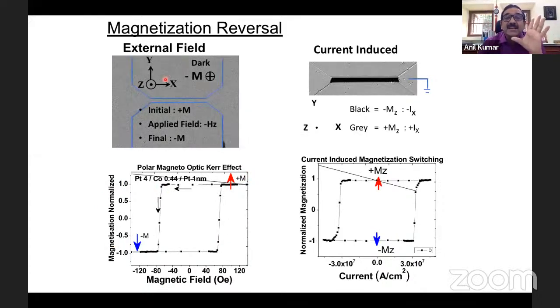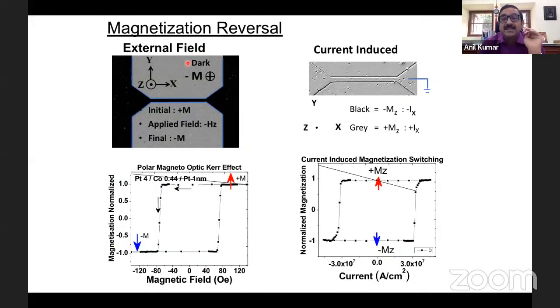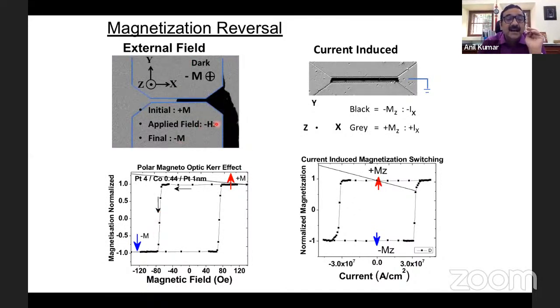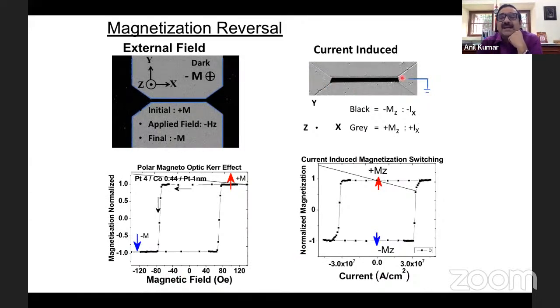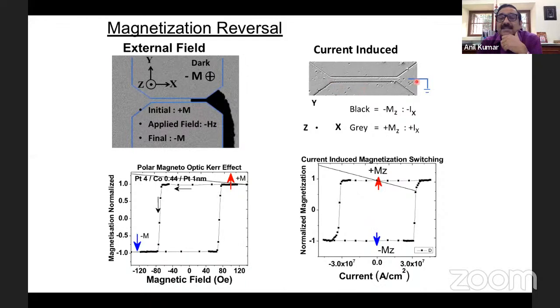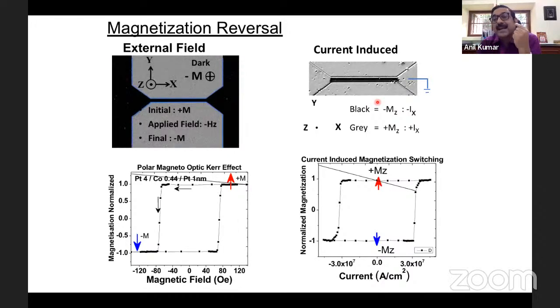So this is a field-induced magnetization reversal, because the applied field is HZ, which is perpendicular to the plane. Now the same system, now I pass electrical current through this. And when I pass electrical current through this, you see that I am switching the magnetization from dark to white only in this small patch. Why is it so? As I told you earlier, what is needed is a critical current density to switch the magnetization. The current density, not the current.